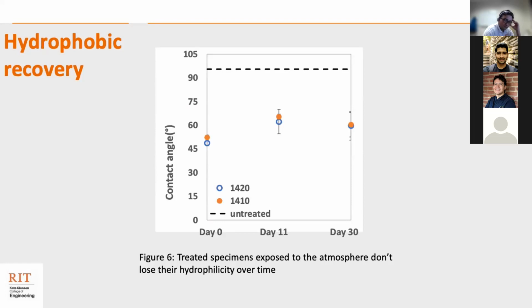As we can see, the black dotted line represents the contact angle for an untreated sample, which remained constant at about 95 degrees, as we talked about before. On the other hand, for the plasma treated samples, the contact angle went from 54 degrees to about 61 degrees and hovered around the same over time. Even though the surface became a bit less hydrophilic, it retained its hydrophilicity over time as compared to an untreated sample.